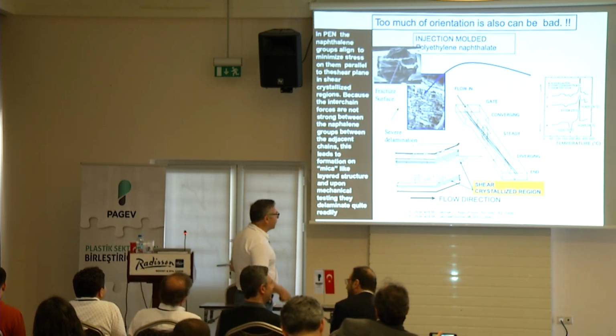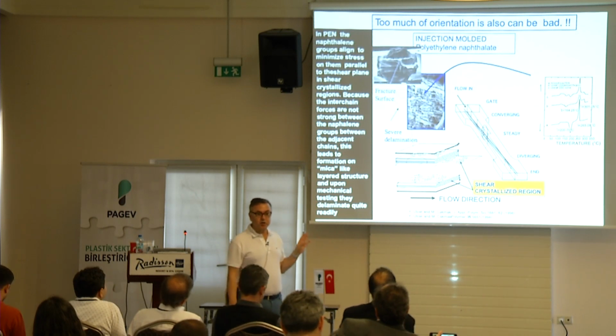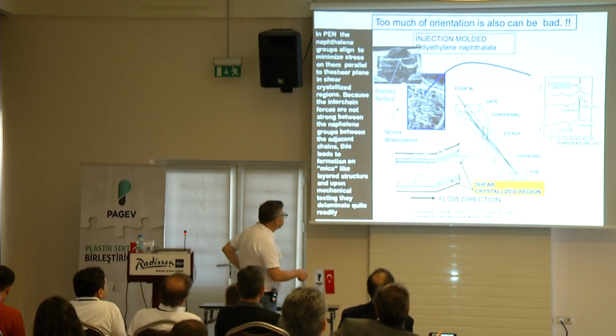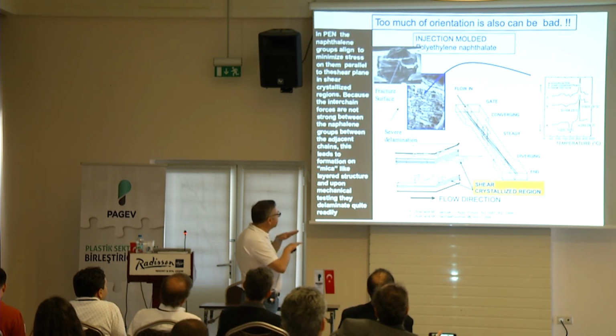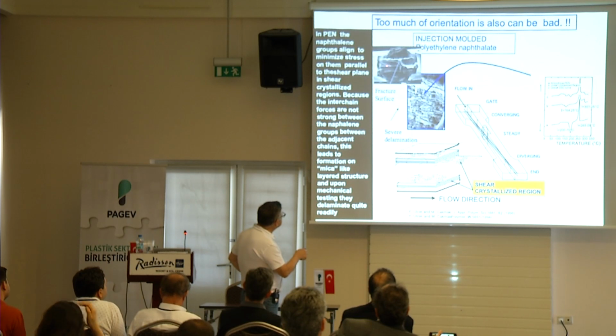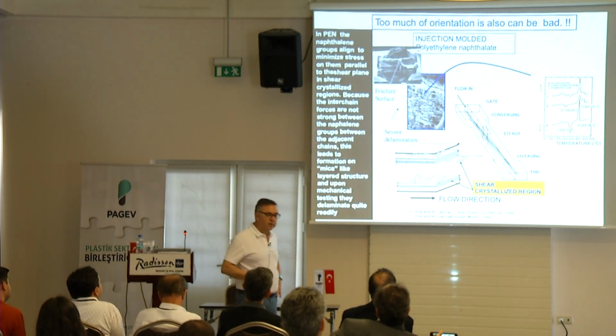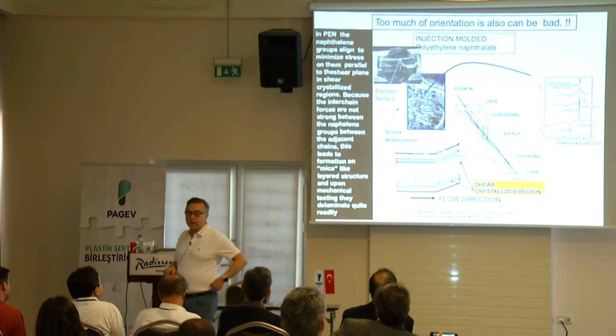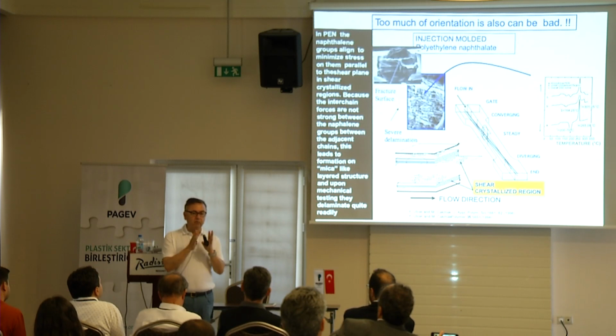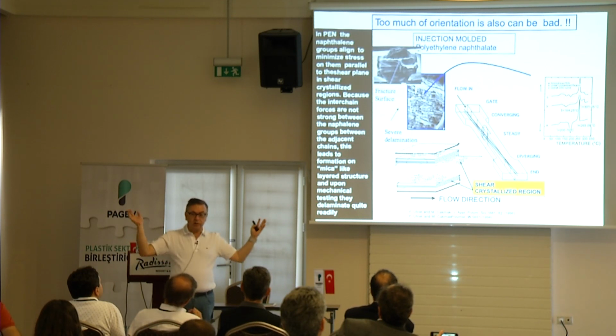This is what happens when you have too much orientation. Polyethylene naphthalate has naphthalene groups that are so easily orientable in the shear zones. So dramatic is it that when Jakub did the impact testing, look at this. They literally exploded where those shear crystallized regions were. Too much, especially when you have a molecule with very poor interchain forces because of the naphthalene nature, it's almost like mica. Then they literally explode.